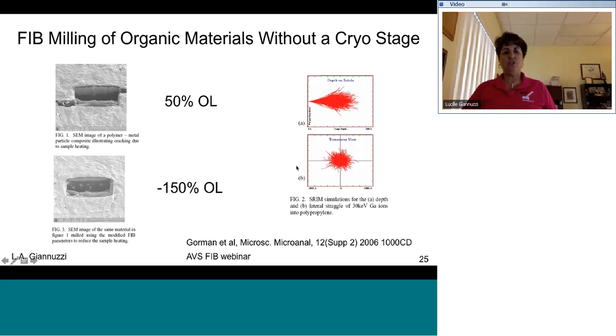inorganic materials, and so you're going to generate a lot more recoil. And so the conventional 50% overlap that we use in, for example, silicon isn't going to work for some of these polymers because you're going to have overlapping collision cascades. And if you have overlapping collision cascades, that means those atoms will never have any time to relax. Those recoils will always be in motion. And in that case, you will get local melting and deform the polymer where you FIB milled. You're not going to heat up the entire polymer, but you're going to locally destroy the